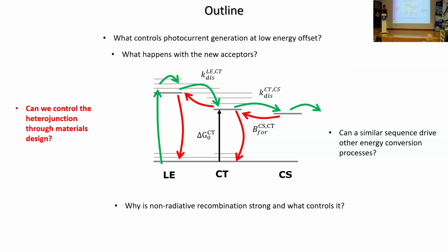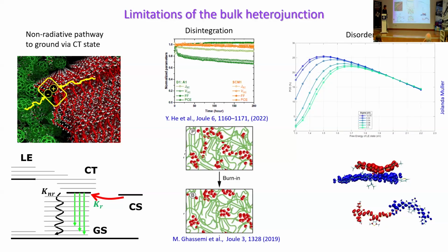So we've been looking at these heterojunction materials and trying to build a framework where we could explore what properties influence the heterojunctions. One of the problems with the heterojunction, well, there are several problems, but some of the problems that I've mentioned, is that the heterojunction creates an interfacial state where recombination to the ground state is quite efficient. We also have the problems that I've alluded to at the beginning. You make this mixture of materials, they're soft materials, and the structure is not very strongly directed. And if you give it some thermal energy, it may disintegrate over time, and that's actually one of the important degradation mechanisms.